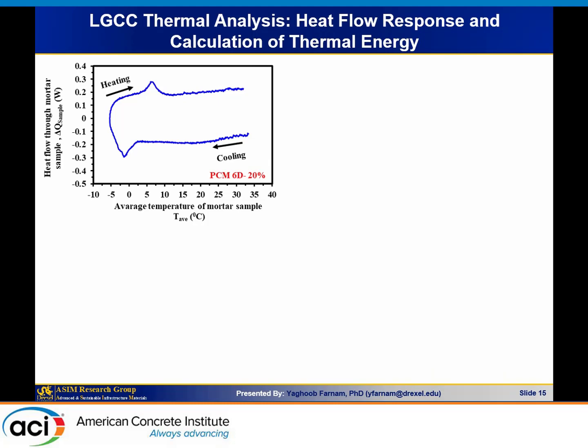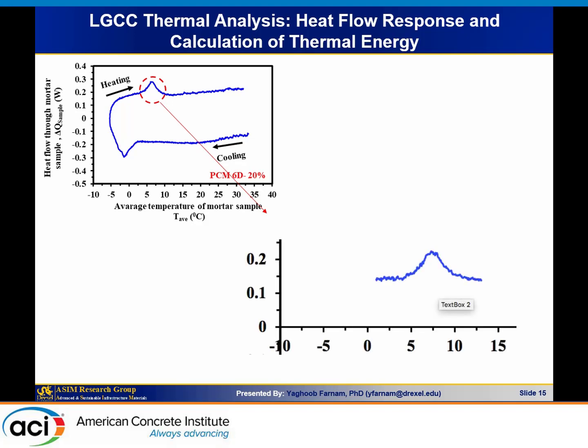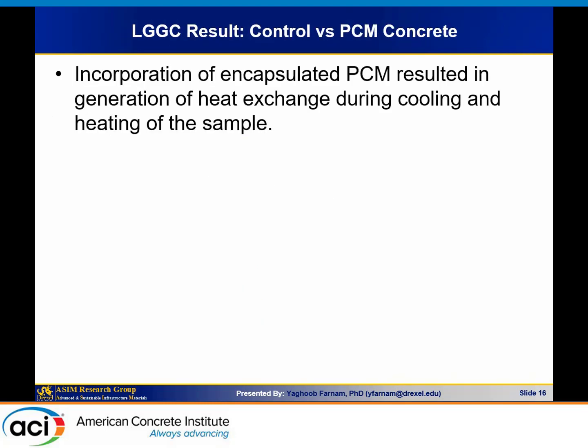So we did that, and this is one of the results that we get from LGCC. Again, heat flow as a function of temperature, something similar to what we get from DSC. And as you can see, we do have that heat spike. And this is the cooling heating cycle. So this is the freezing part. This is the heating part. What we could do is zoom in on that peak and do some integration there, and we could find out the amount of heat release inside my sample. And here we're talking about 3 inches of sample.